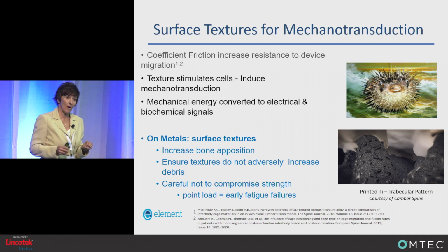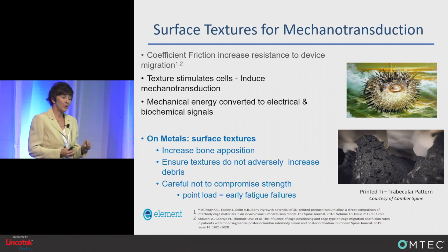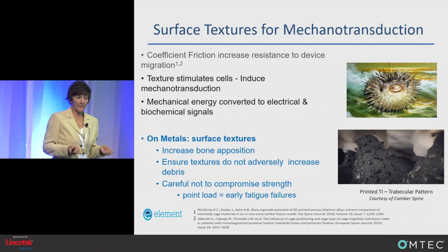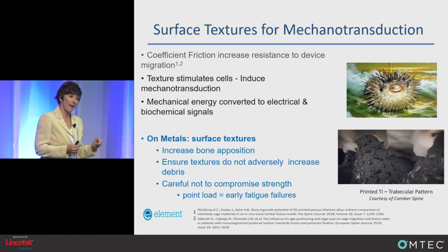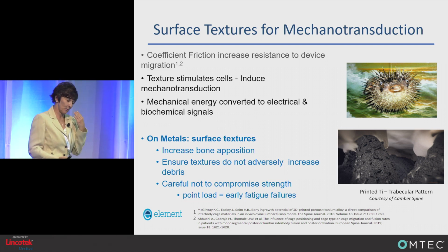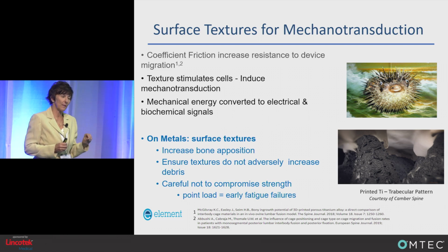If it's too rough, if your peaks and valleys are too high, too deep, you risk potential debris, breakage of these peaks and valleys into the surrounding bone. That's bad. Again, think about the tissue interface. Think about what'll happen if that sheds more debris. But that texture can also stimulate cell behavior.